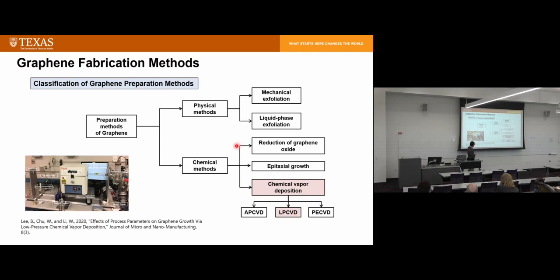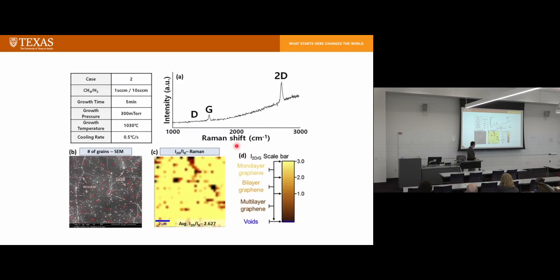In our lab, we studied LPCVD methods. This is one student. He modified the standard tube furnace growth method. He put the tube furnace on a platform so you can move the furnace back and forth, changing its relative position between the sample and the furnace, so that you can study the cooling effect, and that turned out to be a major effect. So we can grow samples in our lab. This is the quality of the graphene, from the student's work.